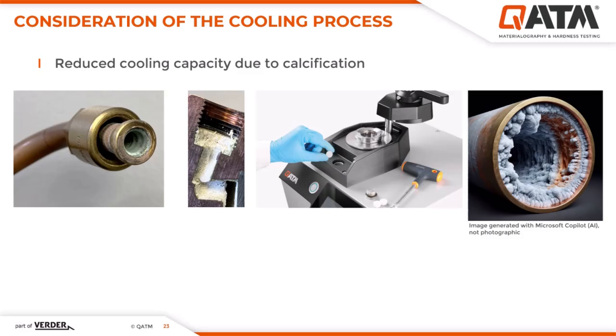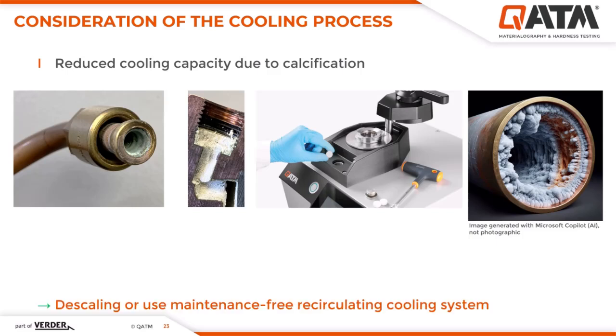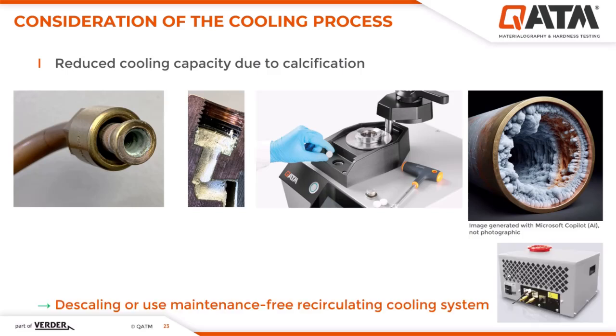Depending on the water quality in the freshwater system in your lab, lime deposits will build up over time in the water pipes and possibly inside the machine. These deposits reduce the pipe diameter and, as a result, decrease the flow rate of the cooling water. Similar to a coffee machine, we offer the option to measure the water hardness during the installation of the machine and to set a suitable descaling interval for a regular cleaning of the cooling system. Supplied descaling tablets and an integrated descaling function in the machine software make this cleaning process easier. Alternatively, you can use a maintenance-free recirculation cooling system to cool your mounting press efficiently.